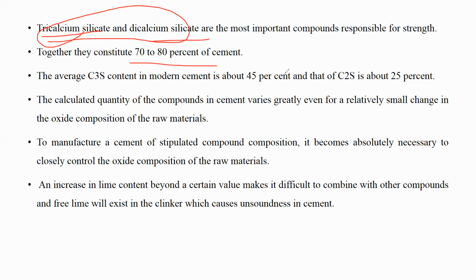An increase in lime content beyond a certain value makes it difficult to combine with other compounds, and free lime will exist in the clinker, causing unsoundness in the cement. Okay, so in the raw material there is lime also, so lime should be added in the proper quantity. If we add the lime quantity more than required, what happens? Cement will become unsound.